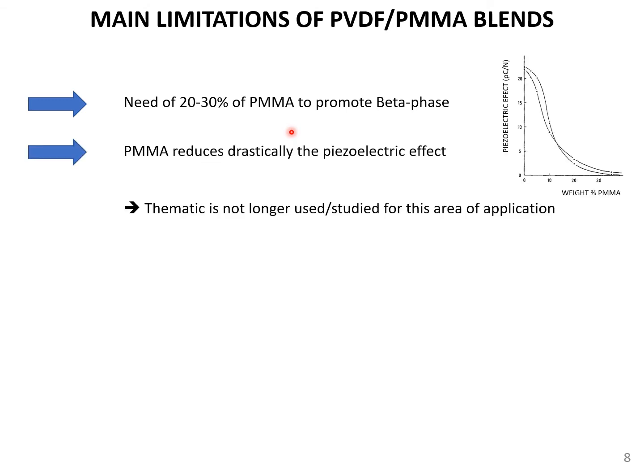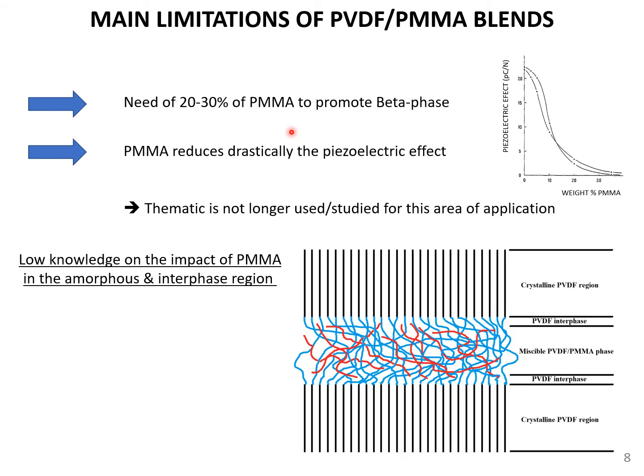There are some limitations based on the PMMA-PVDF blend as reported in the literature. We can see from some papers that you need at least 20% PMMA to promote the beta phase, and other papers have reported that when you add PMMA you can reduce the piezoelectric effect of these materials. Of course, there is a lack of understanding about the real effect of PMMA, particularly regarding what is going on with the effect of PMMA on the crystallization of PVDF, but also what is the nature of the interface, particularly the amorphous region combining the amorphous part from PVDF and the amorphous part from PMMA.